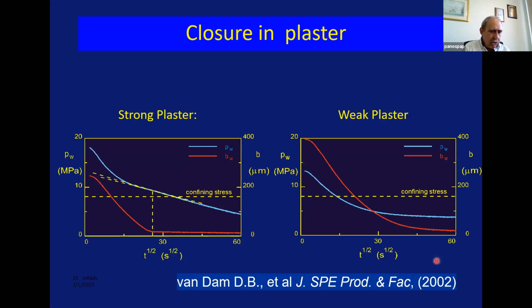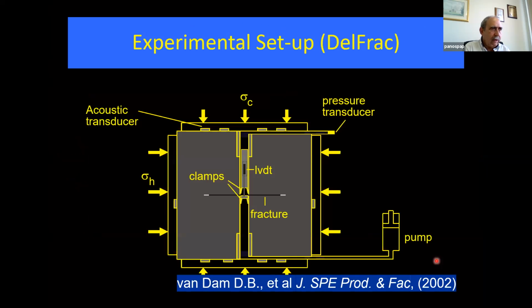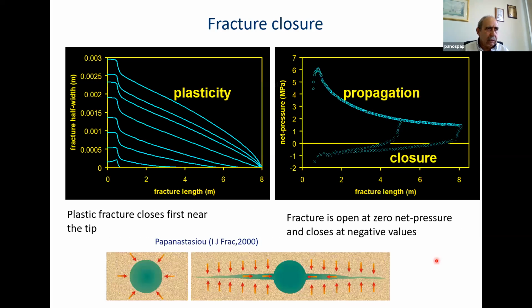The other thing which I forgot to mention, so allow me to go back a little bit here: when the fracture closes first near the tip, the proppant near the tip will be under higher stress, and then it is a matter of equilibrium. The proppant back at the wellbore will be under lower stress. So we need to be very careful with the closure stress on the proppant.